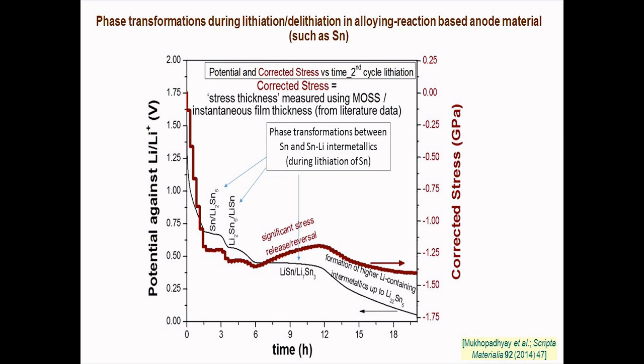This is another example, tin, from our own work, which shows that tin is a classic example where it keeps forming different tin-lithium intermetallic phases during the progress of lithiation. If one looks at the potential profile, for different phases there will be different potentials at which the lithiation is taking place, and the flat region corresponds to the phase transformation region where both the phases are in equilibrium.